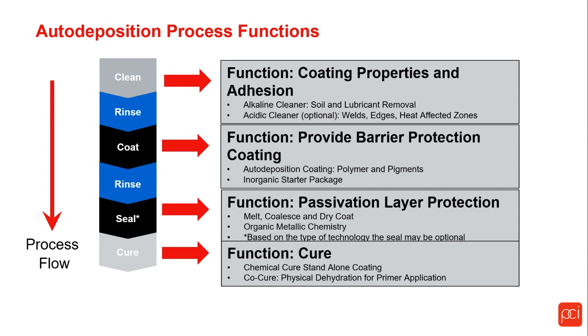But as long as the metal is clean, all you need to do is clean it, rinse it, and as you can see here where it says coat, the auto deposition and the conversion coating are done in one tank. This is a significant difference from other technologies. So you apply your primer coat and your conversion coating in the same bath. The next few slides will show that in a graphic representation. Depending upon the technology used, a seal may be needed, but a seal is not used for all types of auto deposition.